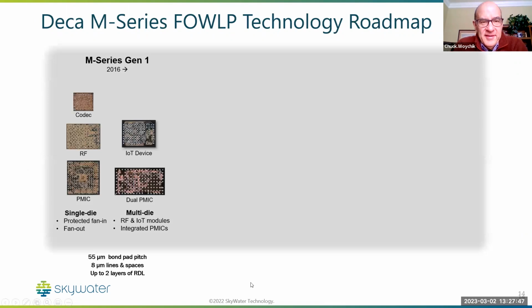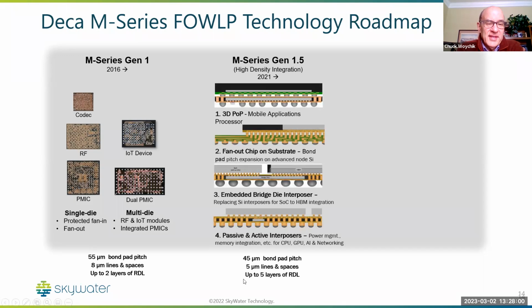So as we get into the fan-out wafer level technology, what's currently being practiced by DECA in Asia is the Gen 1. And this is really a 55 micron bond pitch, 8 micron lines and spaces, up to 2 layers of RDL. And you can see all the different variations there. Also, what's being currently practiced right now is the 1.5, which gets into a finer pitch, 45 micron die bond pad pitch with 5 micron lines and spaces and up to 5 layers of RDL.